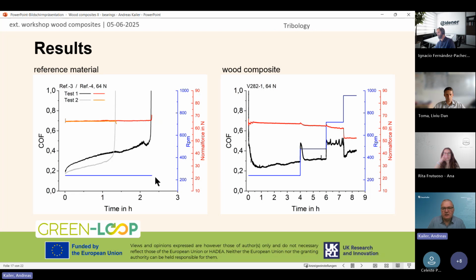speed level was reached. On the right side, you can see the wood composite, where we also see in black a friction coefficient, which started a bit higher, but quickly was reduced to around 0.25 to 0.3, which is not so low as in the pin-on-disc test, but really, really good. And you can see also the rotational speed was increased stepwise to 900 rotations per minute, and so the material was stable while the friction was slightly increased in these different speed ramps.